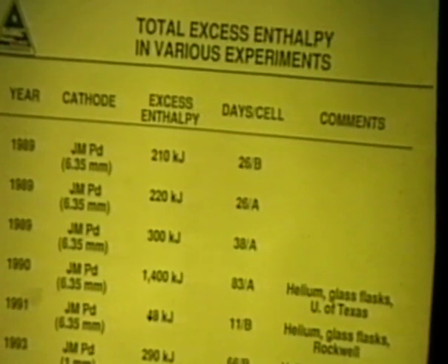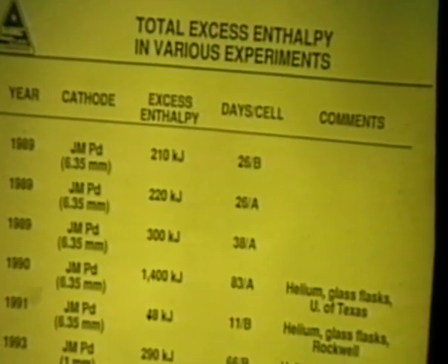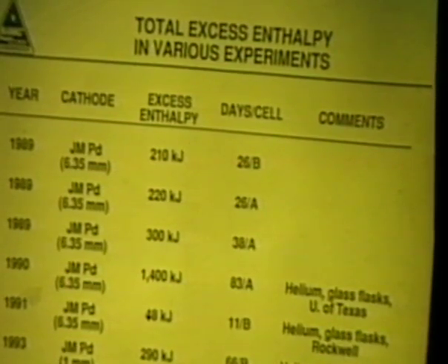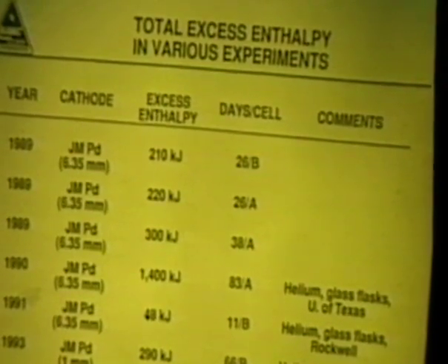But I want to point out, if you assume we had palladium deuteride and completely burn that, you burn all the deuterium and all the palladium from the weight that we had, 4.3 grams of palladium, we would only get 6.2 kilojoules. So chemically, that would be the most heat that we could expect, the most energy. And you see we measured much higher than that, so it does not seem to me that you can explain it by a chemical reaction, even burning the palladium, oxidizing the palladium and oxidizing the deuterium in the palladium.